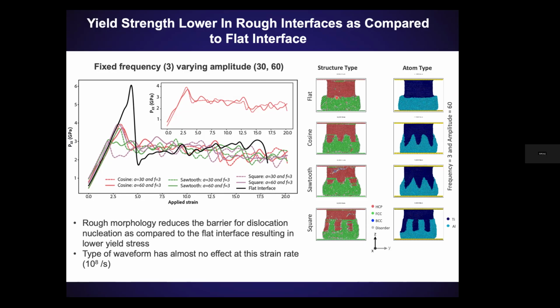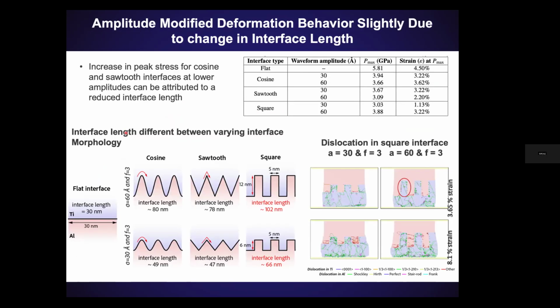And what is yield stress if not the elastic to plastic transition, and plasticity being defined by nucleation and motion of dislocations? So here, by looking at the actual movies, we could understand that having a rough morphology actually drops the yield stress in the material because you have reduced the barrier for dislocation nucleation. The other thing that we got is if you looked at all the different waveforms, to me at least, they look the same at this strain rate, but we needed to delve into it more. So we decided to do an in-depth analysis.